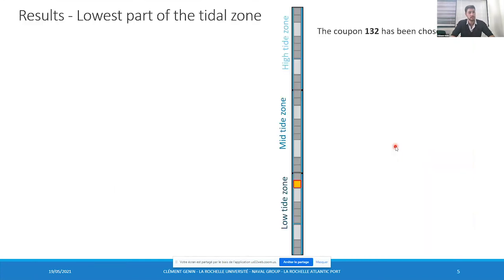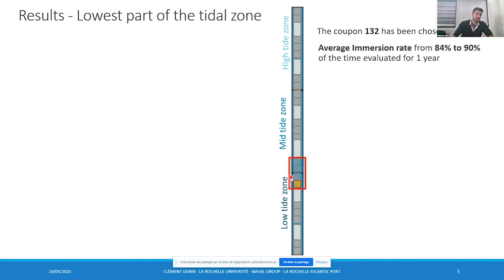Okay, let's start with the results. The first coupon presented here is the 132, which is representative of this area, with an average immersion rate of 84 to 90%. This immersion rate is calculated over 1 year for the time of the immersed phase.